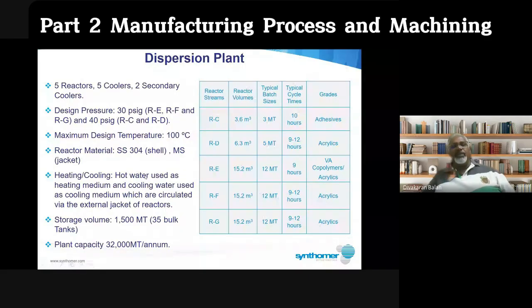All these reactors are designed jacketed, so you have water running around the shell. We call it jacketed because the heating and cooling is done by injecting water. When you cool, you inject normal water. When you heat, you inject steam into that water to bring up the temperature. The shell is internal, where you have the mixer, and the material is stainless steel 304. The jacket, the outer layer, is carbon steel, mild steel. Because we just use water inside that, it is a cheaper design. So inside is stainless steel, outside is mild steel.